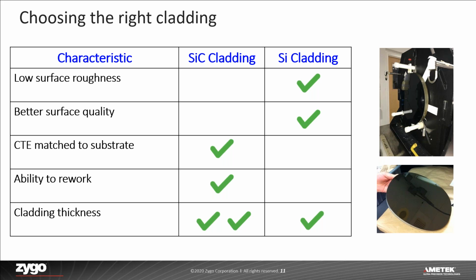With CVD silicon carbide, that can yield good surface figure, but it is limited on roughness and surface quality due to the porosity of the cladding. It does tend to be thicker, greater than 100 microns, so it's a little less conforming to the shape of the base substrate, but may give you some leeway in the event that there is some rework needed. Other things to think about are voids, pits, and inclusions in the cladding, which can also affect the properties.